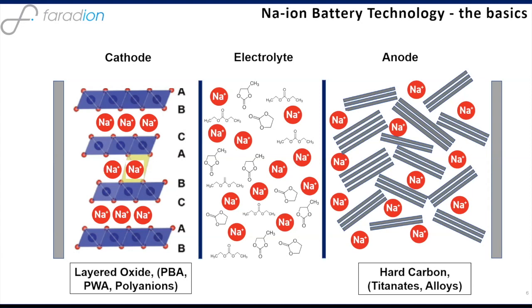On the anode, unless you make modifications to the electrolyte, you generally can't use crystalline graphite as the active material on the negative side. So you have to end up using some kind of disordered carbon, and that generally is a hard carbon material. For certain applications, it's also possible, again like lithium ion, to use titanate active materials or conversion alloy materials. And these may well end up being second generation materials here.